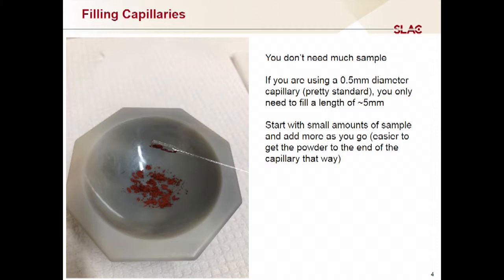and fill it up in stages, because you can actually reduce the chance that you're going to get a clump that gets stuck halfway down the capillary if you're working with small amounts at a time. Once you get a clump that you can't work down, you're kind of stuck, because now you have a little bit at the bottom of a capillary. Everything else is stuck halfway up, which is not really what you would want to do. So this is going to be plenty of material, and it's really not that much.